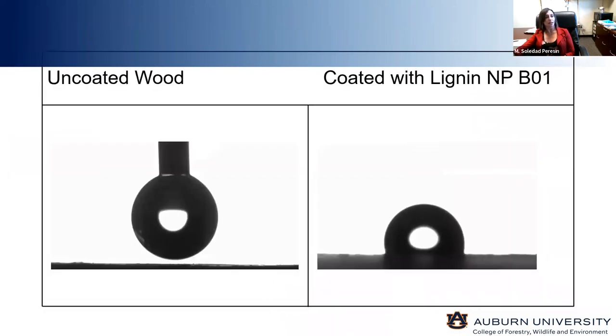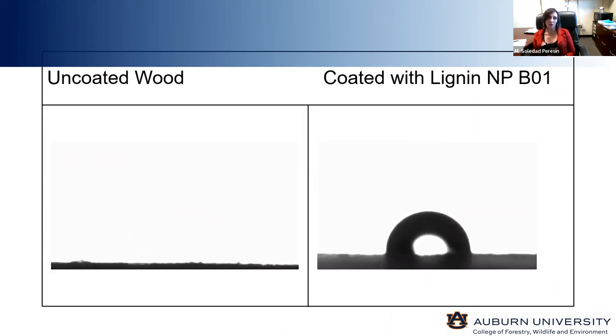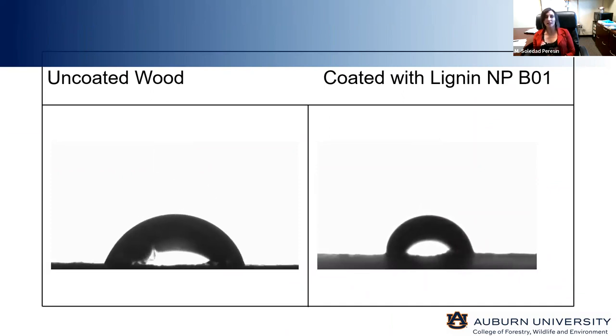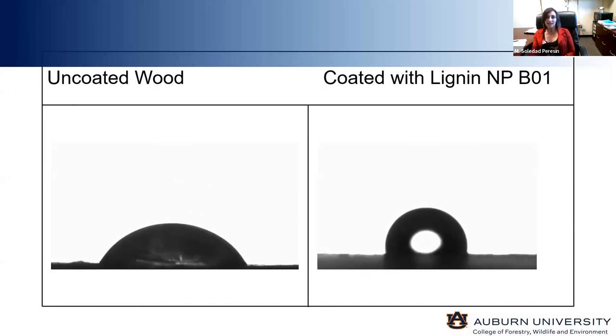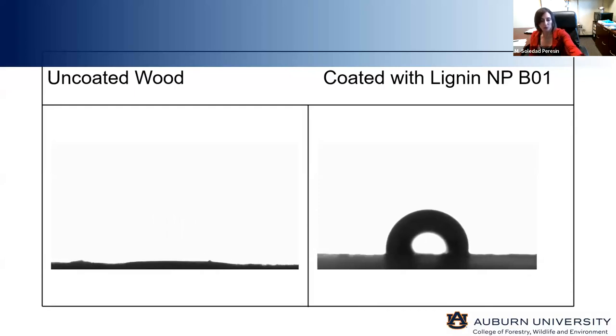And here you can see a video of the uncoated wood and one coated with the lignin nanoparticles that we created, where you can see that the contact angle against water improves significantly in the case of the lignin coated wood particles. So the second part of this talk, and I hope I'm doing well on time,